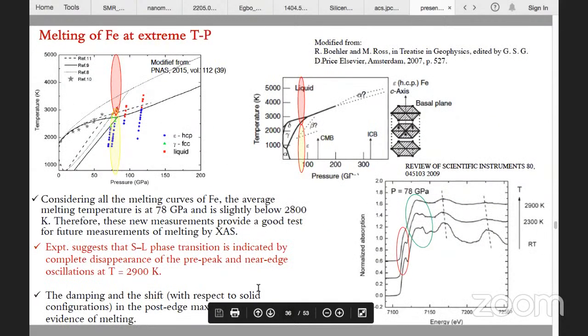What geophysicists are usually concerned about is that people have performed experiments where they produce the phase curve of iron. And what some of the plotted phase diagrams have said is that at about 80 GPa and a temperature of about 2,700 to 2,800 or thereabout, iron is a liquid material. If you put together an aggregate of several phase diagrams of iron, they say that at about 70 to 80 GPa and a temperature of about 2,800, then you have liquid iron, so to say.